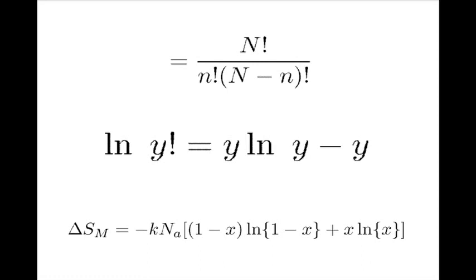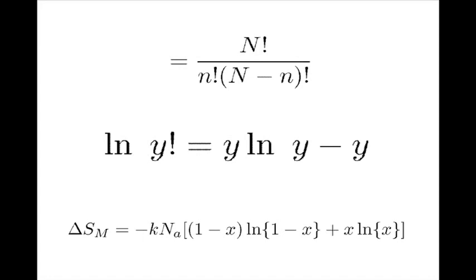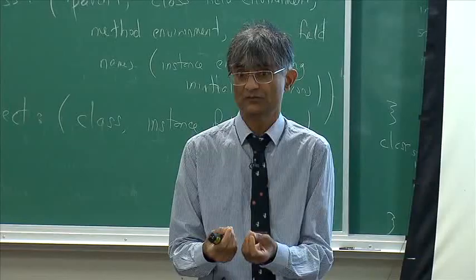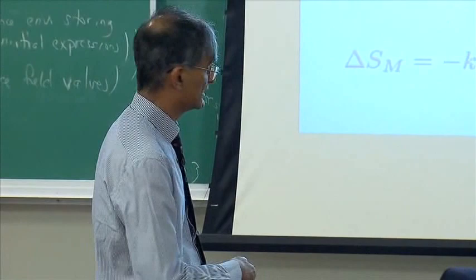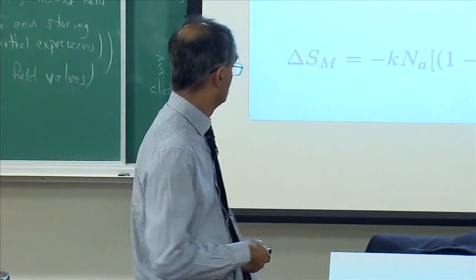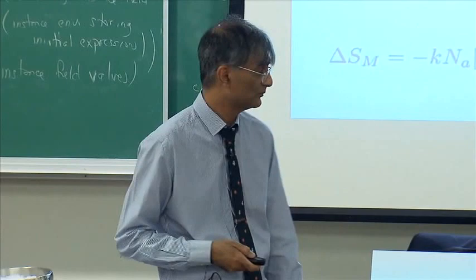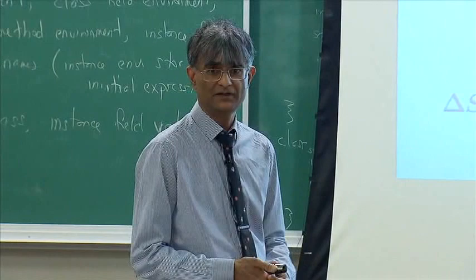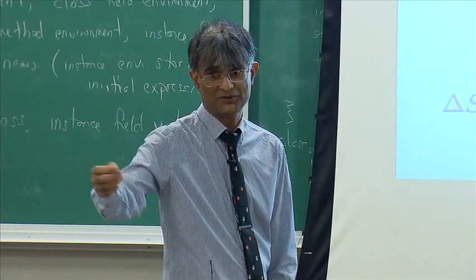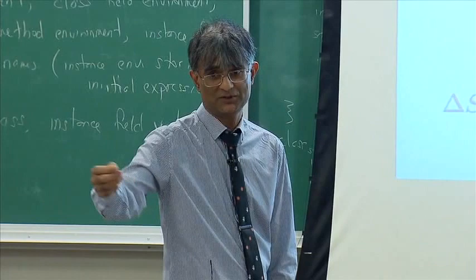Applying Stirling's approximation to the total arrangements and then using Boltzmann's Law gives the classical equation for the entropy of mixing, where x is the mole fraction of A atoms (small n divided by capital N), and (1−x) is the mole fraction of B atoms. This is Avogadro's number (6.023 × 10²³) times Boltzmann's constant k times ln(W). The equation is easy to remember: it's simply R[x·ln(x) + (1−x)·ln(1−x)]. For more components, you simply sum x_i·ln(x_i) over all species. This is the entropy of mixing.